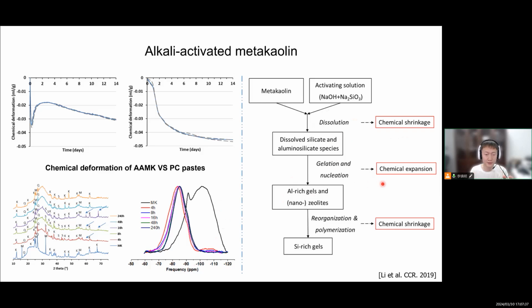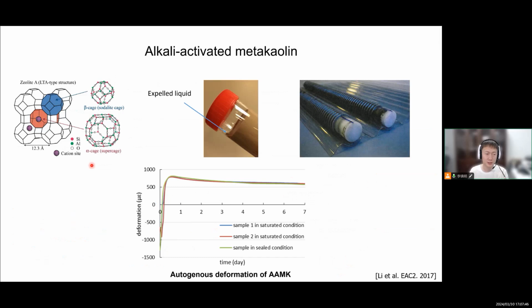This is very interesting. And in the third or final stage, when silica-rich gels are formed, there will be chemical shrinkage again. And this expansion is because of the formation of crystalline or semi-crystalline phases; the solid tends to occupy a big volume, but this volume is not really available for the accommodation of water molecules. So a lot of water is expelled from the matrix. That's the reason why I said this water may influence the measurement, because if we seal everything in a tube, but the water is expelled out, maybe it can induce some expansion. But anyway, that is what we get.